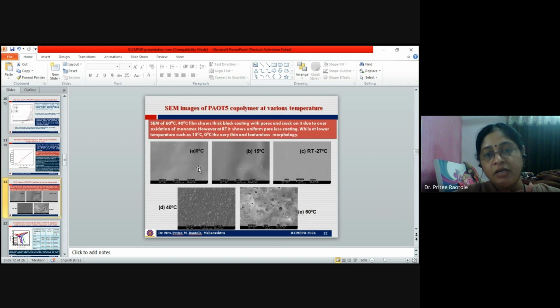Here we can observe the scanning electron micrographs of PAOT5 copolymer synthesized at various temperatures. The scanning electron micrographs at 60 degrees Celsius and 40 degrees Celsius show a thick black coating with pores and cracks on it due to the over-oxidation of the monomer. However, at room temperature, it shows a uniform poreless coating, and at lower temperatures, that is 15 degrees Celsius and 0 degrees Celsius, a very thin and featureless morphology.